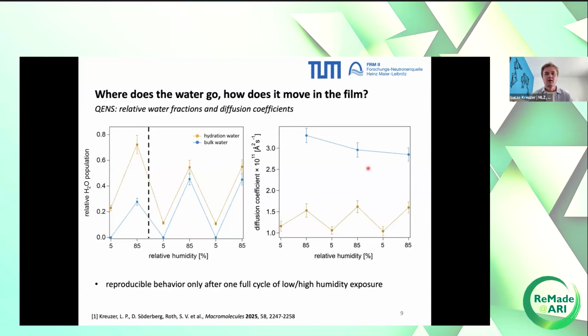For the bulk water, this is still under discussion in our groups, why this is decreasing, why diffusion slows down when you actually have a higher amount of bulk water. We're still trying to figure this out. If you have a clever idea, we should talk. But yeah, so diffusion behavior is also dependent on the amount of water that is present in these films.